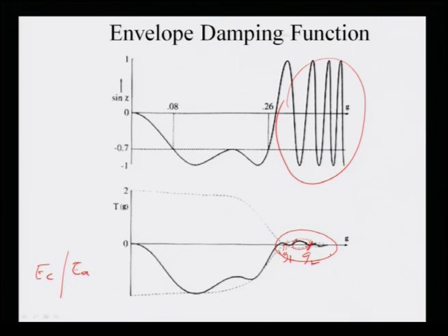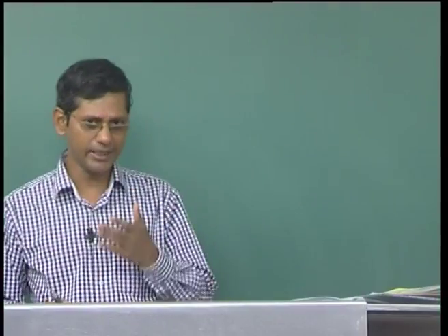Now, knowing all these aspects, how does a real microscopist change or operate the microscope? As you see, defocus has a very strong role to play in getting actual high resolution images, because delta F is a very important aspect, and we have to go to the Scherzer defocus limit to obtain the best resolution image. So how do I achieve the delta F Scherzer in a real microscope? That can be done in many ways.